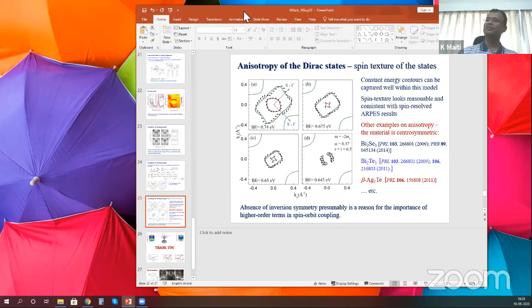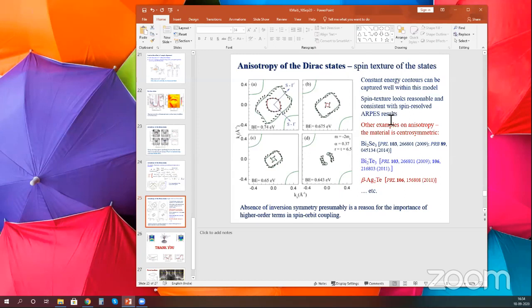But yes, in our experiment, we have done a really detailed optimization and careful studies that I have shown in my plot, that if you optimize the experimental setup at different photon energy, you always end up getting a Dirac cone without a gap. So this means that it is not at gamma point. This cannot happen if you have the Dirac node at the gamma. Right. Thank you. This is a confirmation.